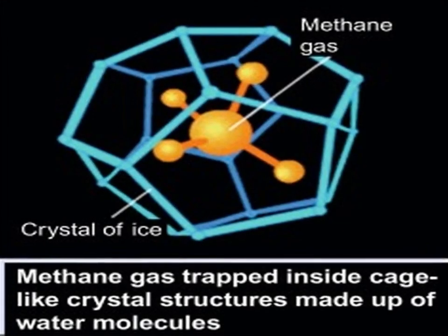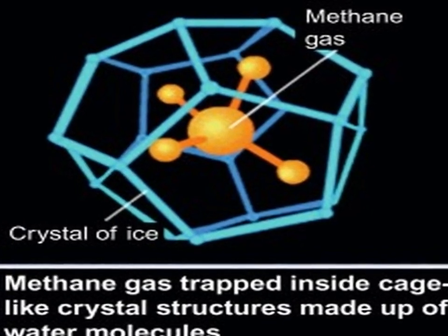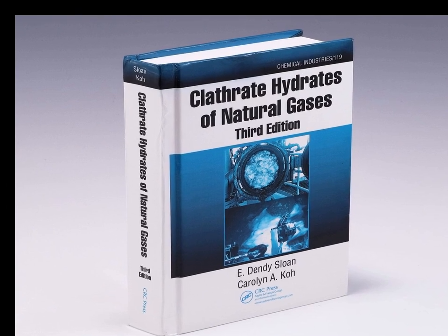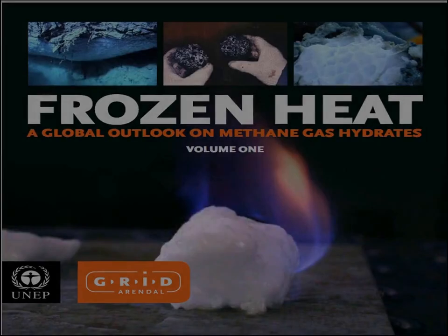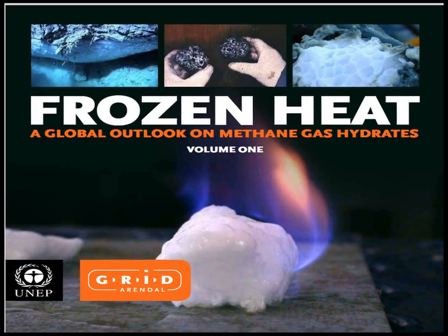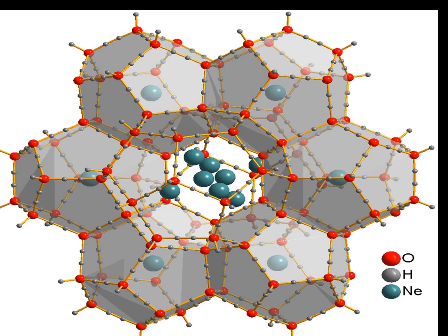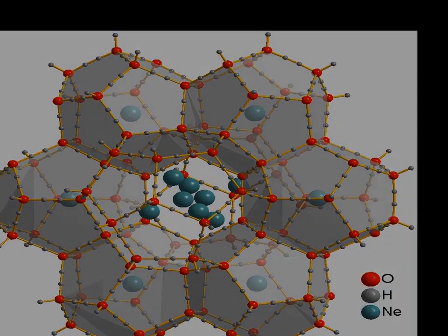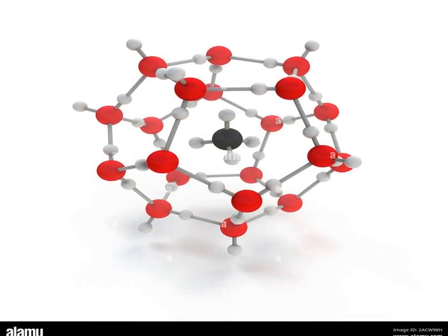Clathrate compounds are a unique class of materials characterized by their cage-like crystal structures, in which guest atoms or molecules are physically trapped within a host framework composed of other atoms, typically forming polyhedral cages. These structures do not involve direct chemical bonding between the host and the guest species, but rather rely on weak van der Waals forces to encapsulate the guest species. Clathrates can be broadly classified into gas hydrates, inorganic clathrates, such as intermetallic clathrates, and organic clathrates, each defined by the nature of their host frameworks and encapsulated guests.